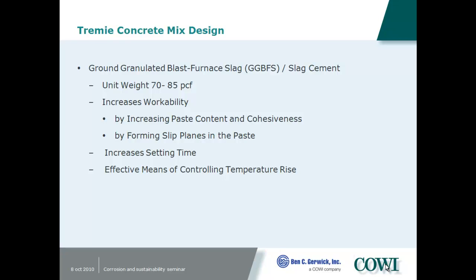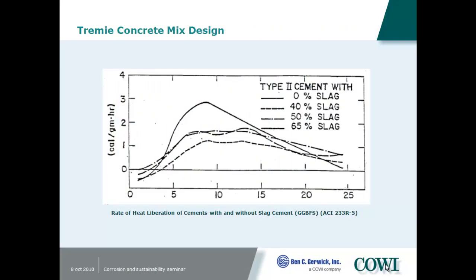So here's the granulated blast furnace slag. It gives you the unit weight. It's actually lighter than cement, so it can have an advantage that way. Weight's important. If nothing else, this was a seismic zone. By having a lower density, you had a little bit less seismic demand. This does show the rate of heat of hydration for a typical slag. So without any slag, you'd have a lot more heat, and it would come earlier. With a 65% blast furnace slag, it would be less production of calories.